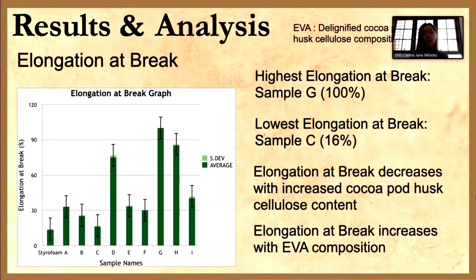Moving on, we have the results obtained for the elongation at break values. The highest value was found within sample G at 100%, while the lowest was at sample C at 16%. Elongation at break measures how much samples can be stretched before they break, as a percentage of their original length. Thus, elongation at break states the sample's capability of undergoing deformation, while also indicating the ductility of such a sample.